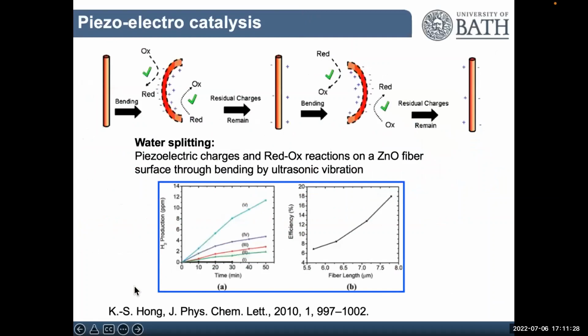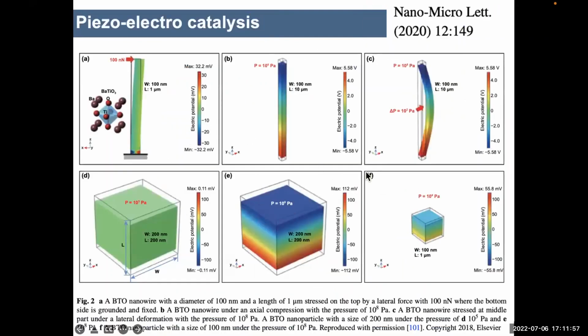And I think the very early work, again, this is not from Bath, is by K.-S. Hong, looking at application of ultrasound to zinc oxide materials. And as Haito nicely explained, when you have these rod type structures, you induce bending, and that bending induces higher strain, which develops higher changes in polarization and more charge. And there's a lot of very nice analysis of what voltages. And I think a characteristic of these piezoelectric materials tends to be high voltages, even as a sensor or as a particle. And so generating the necessary voltage for a chemical reaction is potential. But the downside is that they generate relatively low levels of charge. So they're high voltage, low charge, and how do you mitigate those effects?